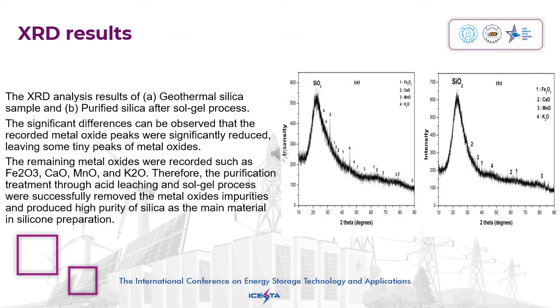The XRD analysis results show significant differences: the recorded metal oxide peaks were significantly reduced, leaving some tiny peaks of metal oxides. Therefore, the purification treatment through acid leaching successfully removed the metal oxide impurities and produced high purity silica as the main material in silicone preparation.